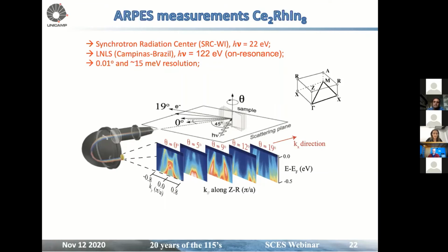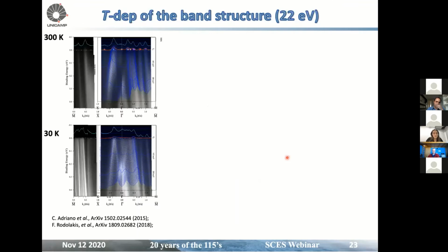We have a band structure that is an energy as a function of momentum, and for those experiments, we rotate the sample in front of the beam, and so then we access the other values of the momentum along the Brillouin zone. So that's the temperature dependence of the band structure, pointing here that is in low energy. So I'm comparing 30K with 300K.